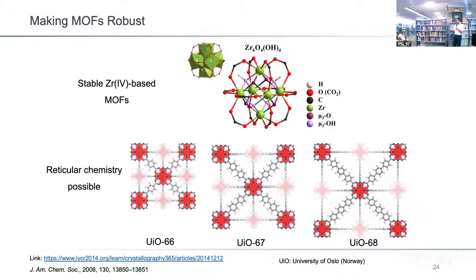And what they showed is this idea of reticular chemistry, which I showed in a few slides before, that if you change the ligand units, if you go from 1-phenyl to 2-phenyl to 3-phenyl, you're essentially still getting the same topology, but the porosity keeps increasing and you're not getting any different structures. If you have the same geometry of the building units, you can end up getting the same self-assembled structure. So again, the idea of reticularity was demonstrated in this, but the most important takeaway from this example was the stability of MOFs by choosing the right building unit.